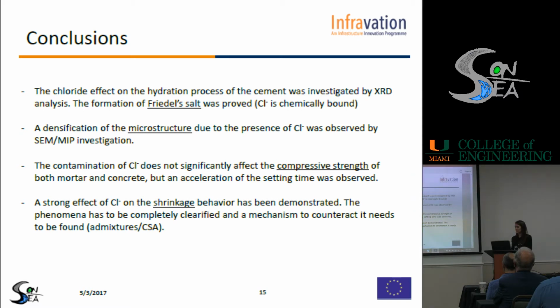So, in conclusion, we can say that the chloride effect is very important in the hydration process of the cement, and we investigated it through XRD analysis. So we proved the formation of Friedel's salt. Then a densification of the microstructure was proved through SEM and MIP investigation. And then the contamination of chloride does not significantly affect the compressive strength in both mortar and concrete, but it produces an acceleration of the setting times. And finally, a very strong effect of chloride was observed concerning shrinkage behavior.